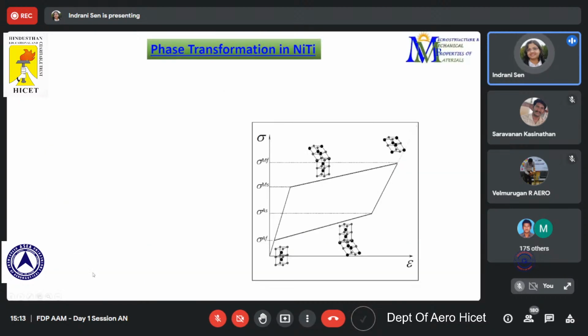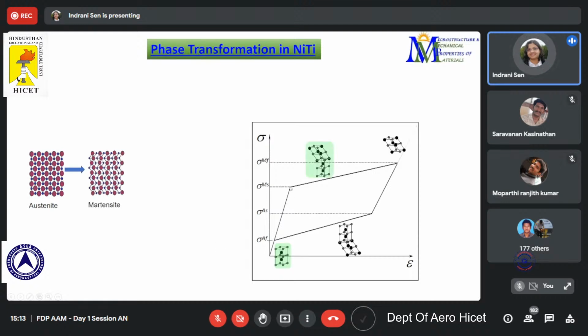Now what happens when we are simply applying stress is that initially there is an austenite structure. This structure here is a cubic austenite structure, and when we apply stress, this is a typical stress strain curve that you're familiar with. When we apply a particular amount of stress, known as the martensite start stress, this austenite structure starts converting to martensite. And by the end of this level, which can be either flat or with a very little slope, this martensite conversion is complete, and detwinning has also happened. You can see that initially this is a twin structure and later on it is getting stretched.